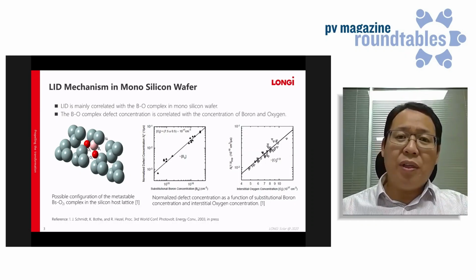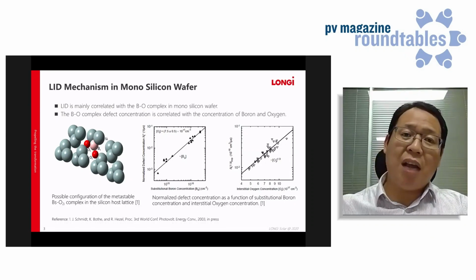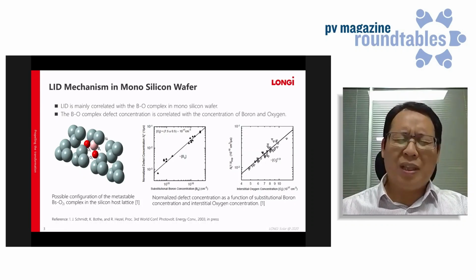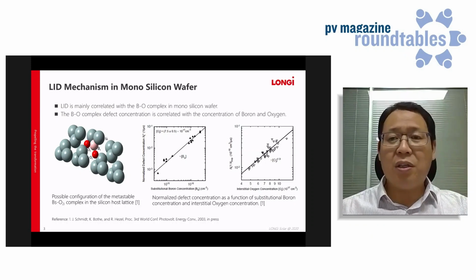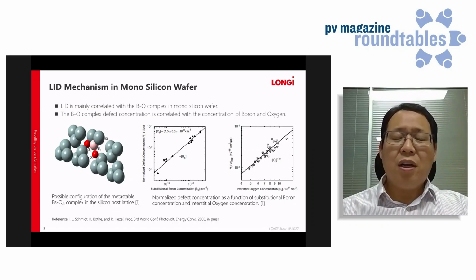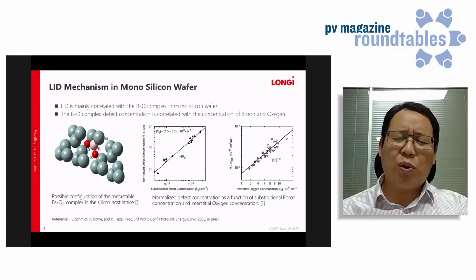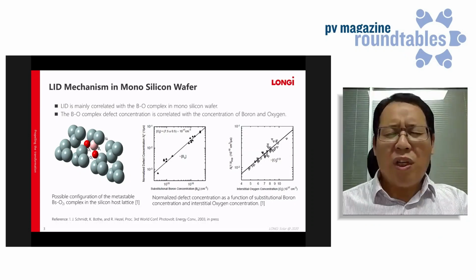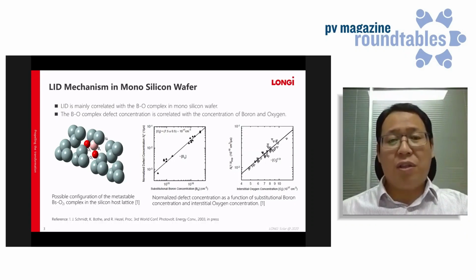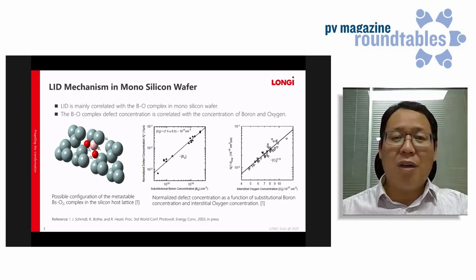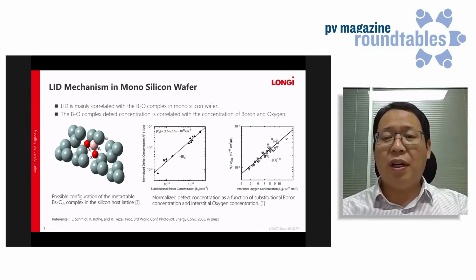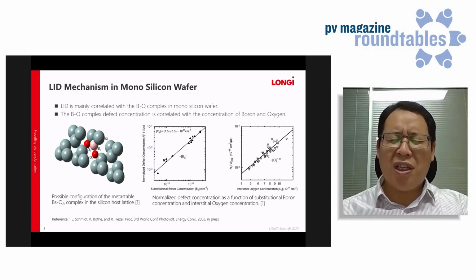As we know, boron is the element used as a dopant in the P-type silicon wafer. Also, during the production procedure, some oxygen remains in the silicon wafer. In the light soaking, the boron and oxygen combine into a complex. That boron-oxygen complex can generate recombination of the minority carrier in the silicon wafer, which will reduce the efficiency of the cell. That caused the degradation of the module. We also know that the boron-oxygen complex defect is related with the concentration of the boron and oxygen. The higher the concentration of the boron or oxygen, the higher degradation it will cause.